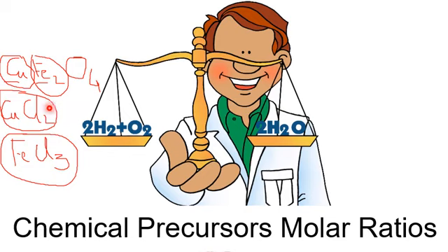Okay, so copper chloride molar ratio 0.1, whereas the iron chloride molar ratio is double, 0.2. They are incorporated separately in a water solvent, in a beaker, and usually it is 100 ml. Okay, please note that if we are going to prepare a 1 molar solution, we need 1 liter of the water.